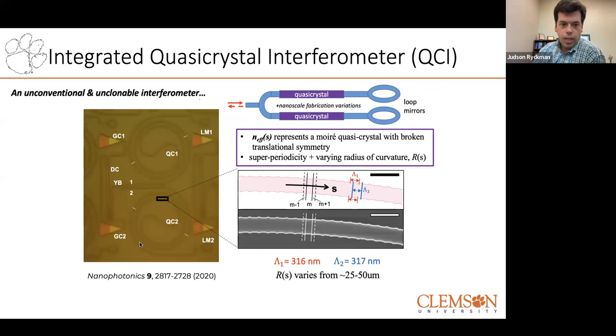So as we look at this device, this is a photonic circuit we made. It's all silicon, but it's on insulator, of course. These waveguides are about 220 nanometers in thickness, about 500 nanometers in width, sitting on an oxide cladding, and they're also overcoated with an oxide. What we do, if you're familiar with an interferometer, is split light into two different paths and look at the phase delay. One simple way to do that is a Michelson interferometer.